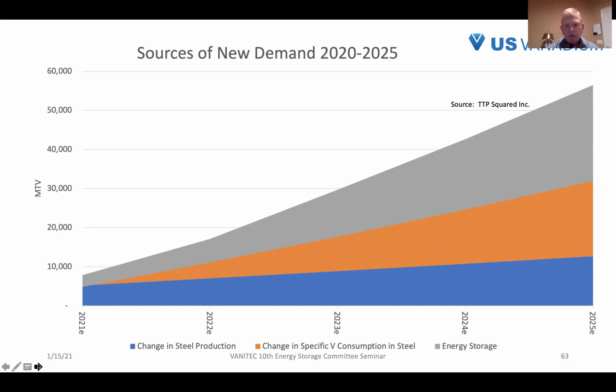So that growing specific consumption rate is going to become more and more important. We see that rate increasing pretty much every year, and we think that rate of change will accelerate going forward due to the economic drivers. And then on top, we see our forecast for vanadium going into energy storage. And as you can see, by the time we get out to 2025, our projection is that the growth in consumption from 2020 will be fairly dispersed between these three factors, but energy storage does seem to be the biggest opportunity. Next slide, please.